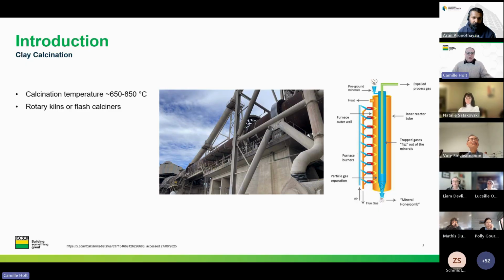For kaolinite, this dehydroxylation can occur at temperatures in the range of 650 to 850 degrees Celsius, which can depend on the equipment being used to calcine the clay, the scale, as well as the properties of the clay. At an industrial scale, calciners can take the form of a traditional rotary kiln, like those used to produce clinker, or a flash calciner. In this project, the flash calciner was used to produce our clay. Whilst calcination does add more processing steps, including treatment at high temperature, kilns are run at about half the temperature used for clinkering, so there's a carbon saving compared to cement.